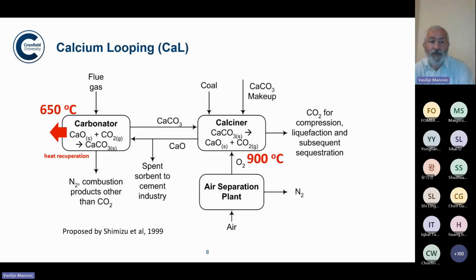So the process is schematically presented here. And as you can see, we have two main reactors, which are the carbonator and the calciner. We operate the carbonator at 650 centigrades. In that reactor, we have calcium oxide reacting with CO2, and the saturated sorbent is basically partially carbonated calcium oxide, because this reaction never happens 100%. We will see it's never going to happen with 100% conversion.